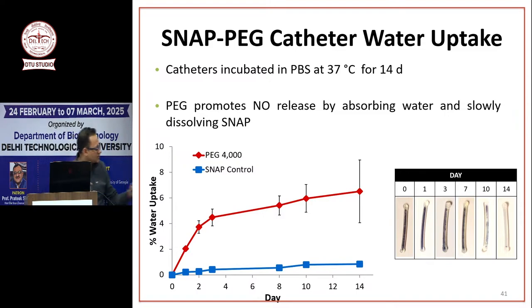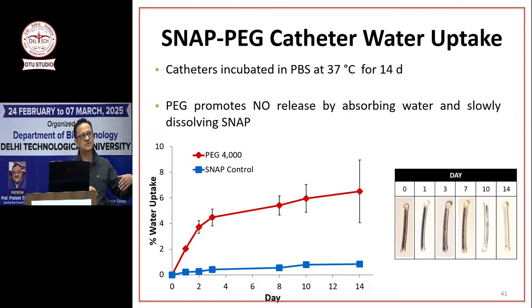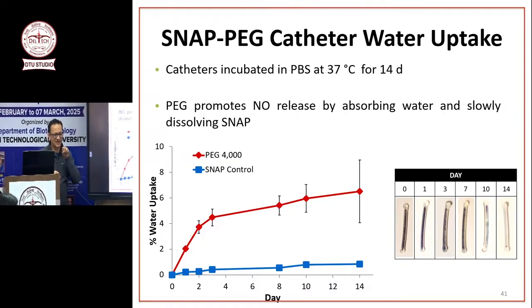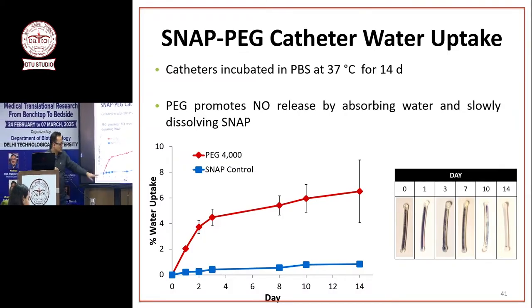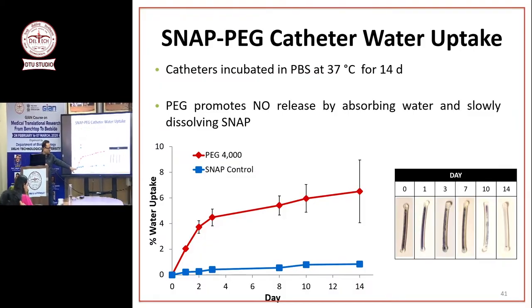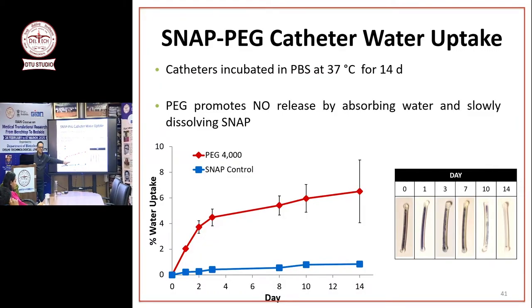Actually, I'm so sorry, I said this was NO release. This was not, I just saw. This is water uptake. So of course, if you have more water uptake, you can release more nitric oxide. With only SNAP powder, water uptake is very low in that lumen. But if you have PEG in there, you are helping with more water uptake, which can help in more nitric oxide release.